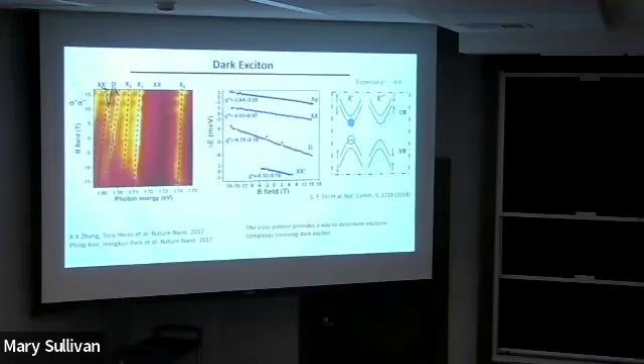But now this out-of-plane dipole radiation does not have this threefold symmetry protection anymore. You actually don't have the same valley physics anymore. So the light is actually not circularly polarized. It's actually linearly polarized, the P polarized light. As a result, this one can be decomposed into both left and right circularly polarized components. As a result, if you apply a magnetic field, this light splits into two branches. One is redshifted, one is blueshifted. That will be a smoking gun evidence of dark exciton.